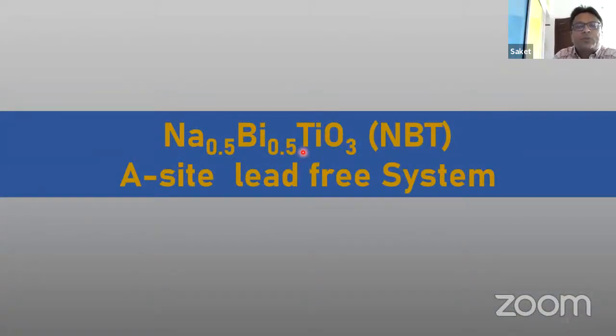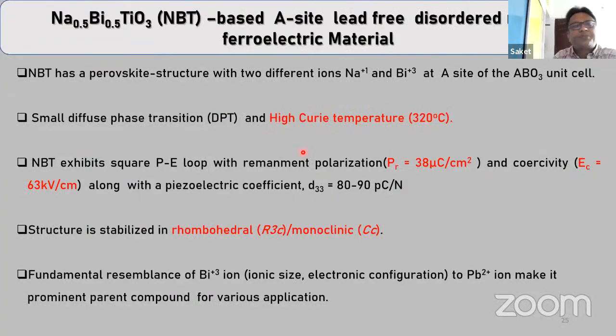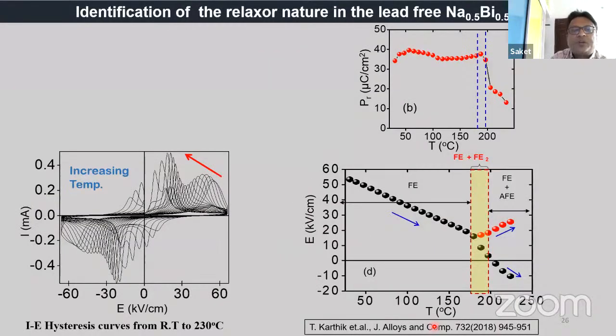So right now, NBT, this is the same system. Why have we selected this material? The Curie temperature is high and the polarization value is high, but d33 is less as compared to lead. These are the systems instead of lead, because bismuth has a lone pair of electrons like lead. So if you are replacing the lead, it is also doing the job that the lead was meant for.